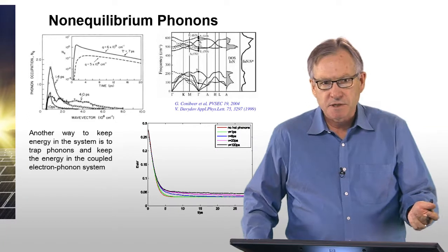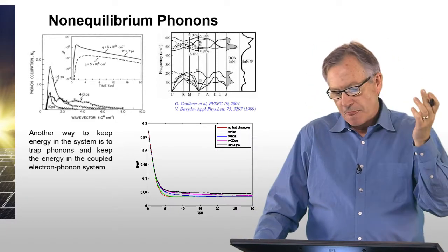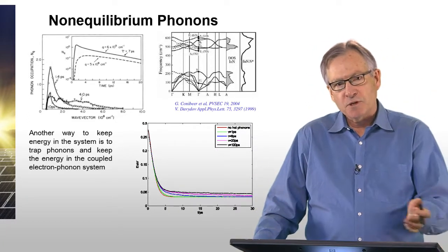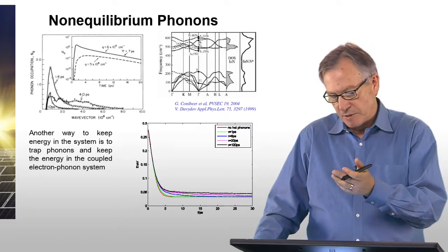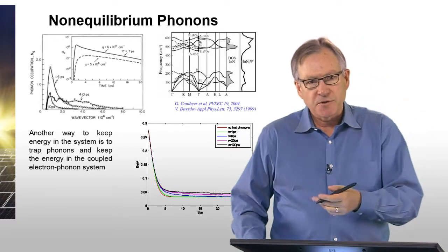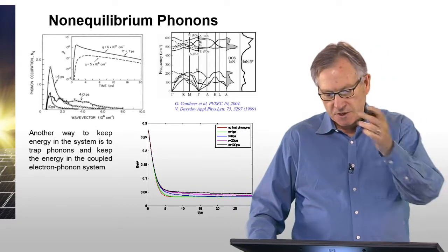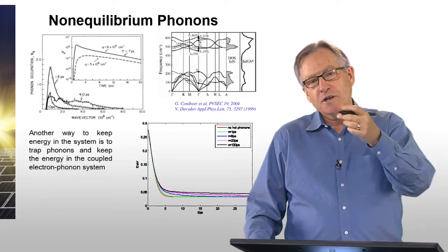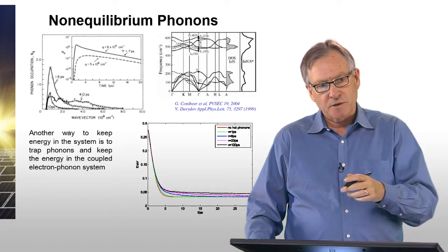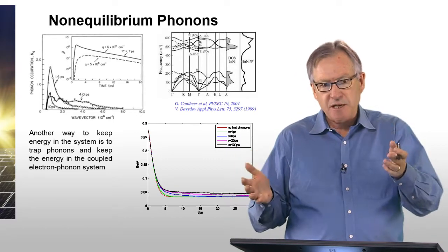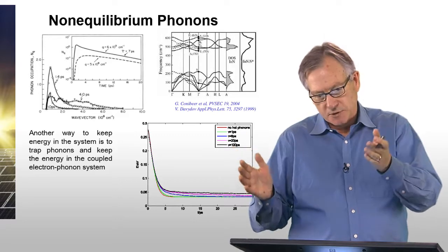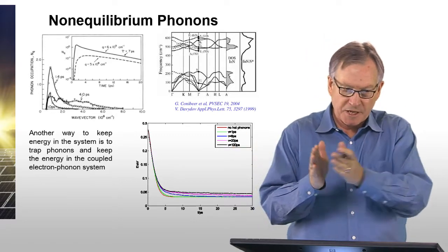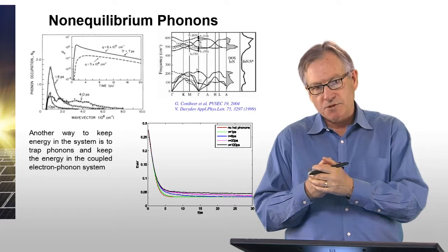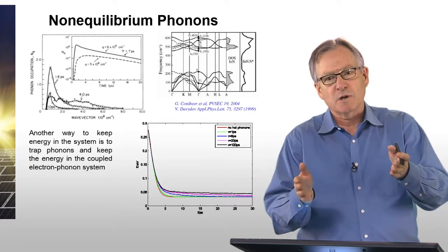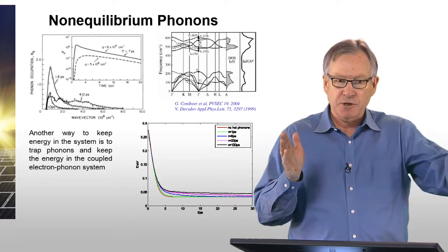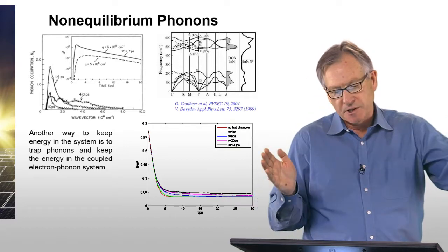So again, the idea in this particular case is that when electrons emit an optical phonon, which is the primary energy loss mechanism, optical phonons have a very slow velocity and they hang around, and so they don't leave the system. It's only when an optical phonon decays to an acoustic phonon, and acoustic phonons, just by their name, are what carry sound. Acoustic phonons are responsible for the propagation of sound within a crystal. And more importantly, they're what carry heat away from a certain area. If you have a hot spot, acoustic phonons carry the heat away.